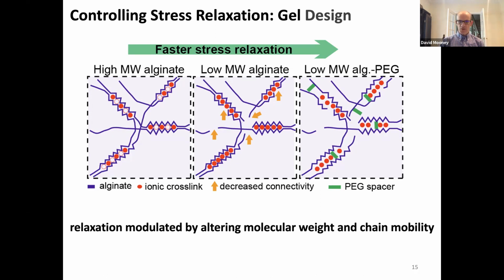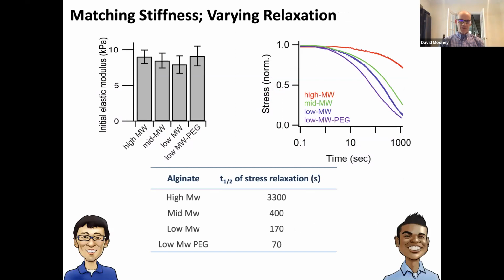The result of this is one can readily form families of hydrogels where we can match the stiffness to be very similar, but have very distinct rates of stress relaxation, here at the bottom characterized by the half time of stress relaxation. And for this grouping, it goes from around 3,300 down to 70 seconds. This next set of studies, in which we really began to explore the impact of viscoelasticity on cell behavior, were done by Ovi Chowdhury when he was a postdoc in the lab, and he now runs his own laboratory at Stanford University, and Luo Gu, who's now at Johns Hopkins as an assistant professor.